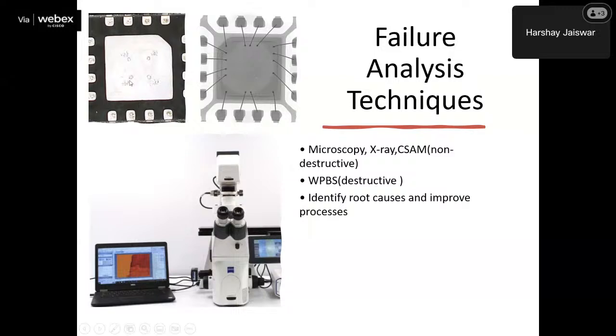It's a VI inspection image. And to the right of this, you see an X-ray image of the same package, 3 by 3 millimeter. Inside you can see the different wires connecting to the different pads. With X-ray, we can see after stress that no bond wire is broken, meaning the device survived, so the bond wire is strong enough. And on the lower side, you see a picture of a microscope where we do the visual inspections.